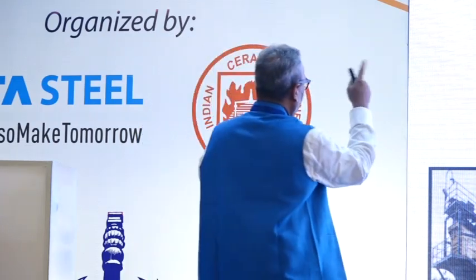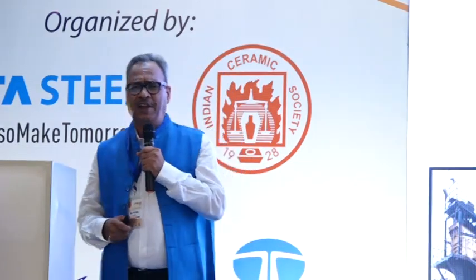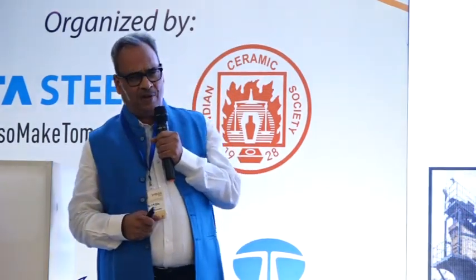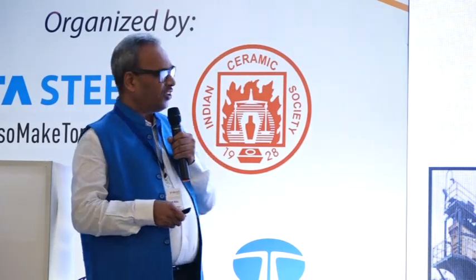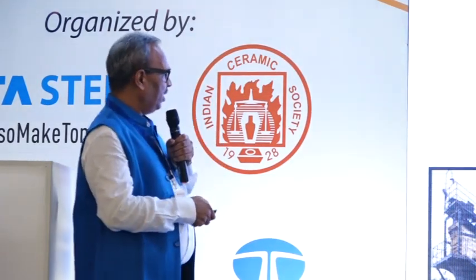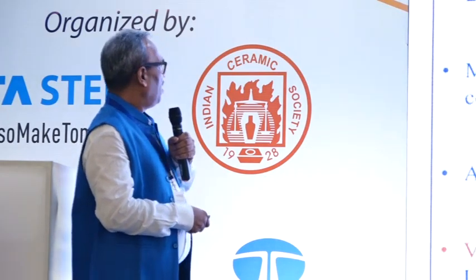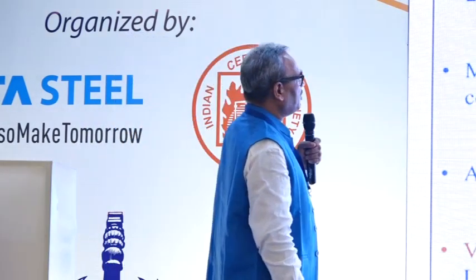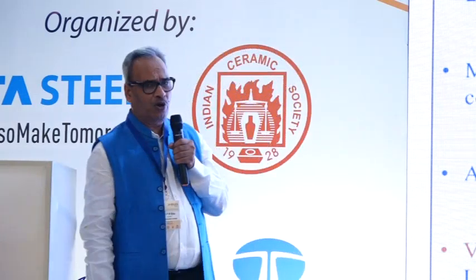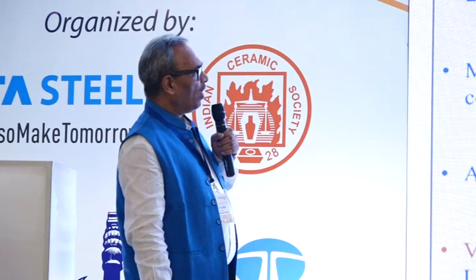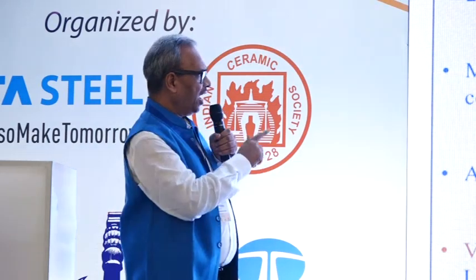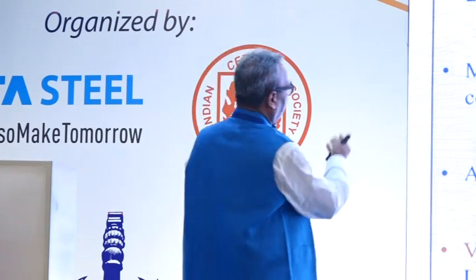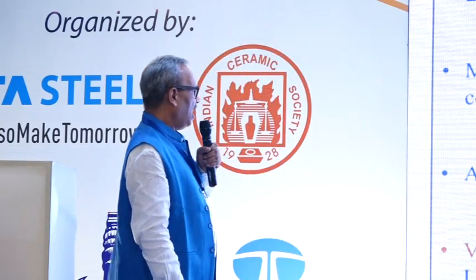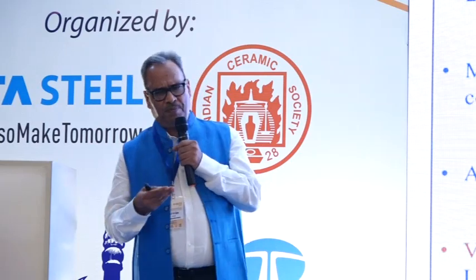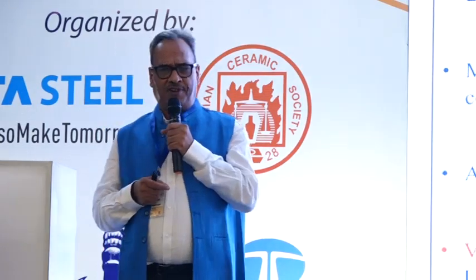So we visited that plant, and we discussed how this plant can be modified for producing sand using the LD slag. And after discussion, we took up a research study. So processed LD slag as a fine aggregate was evaluated for different physical, chemical, and mineralogical compositions also, whatever has been laid down for another type of aggregate in IS 383. Then mineralogical composition, as I said, was analyzed also. And the problem with the LD slag is the dimensional stability.